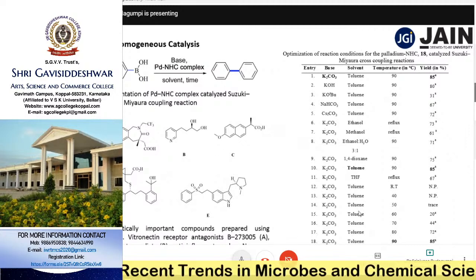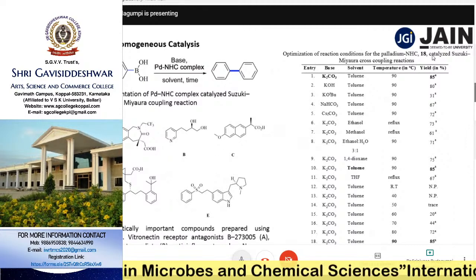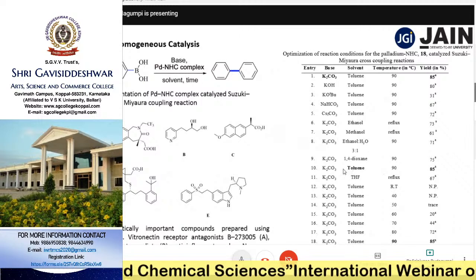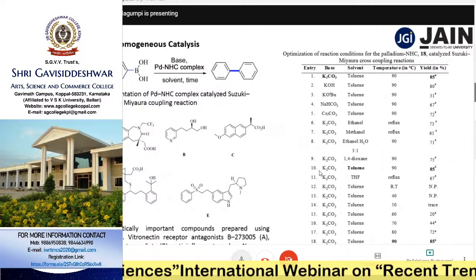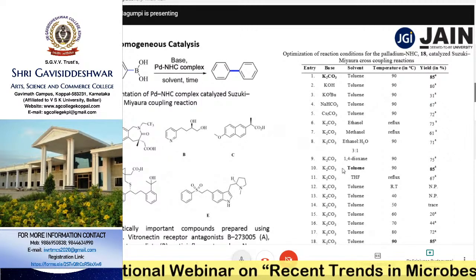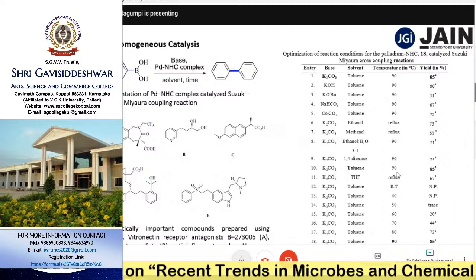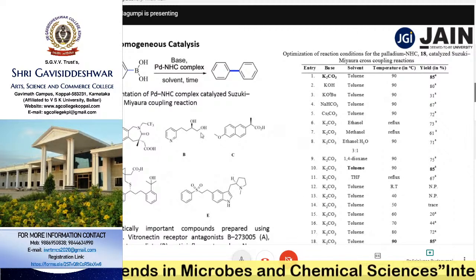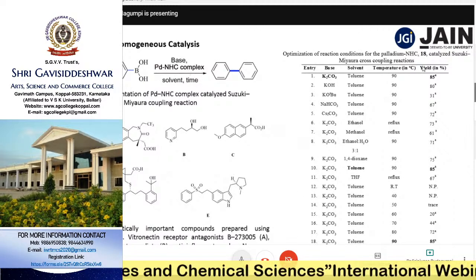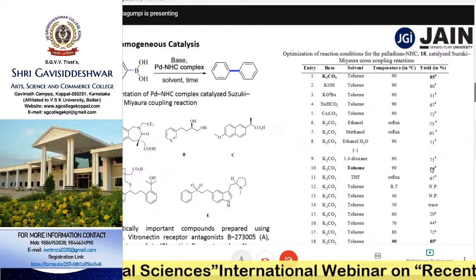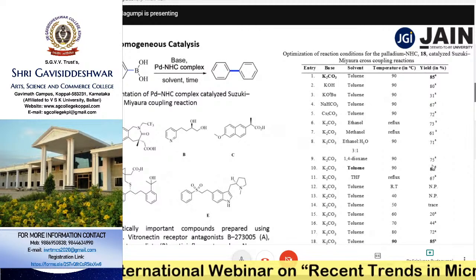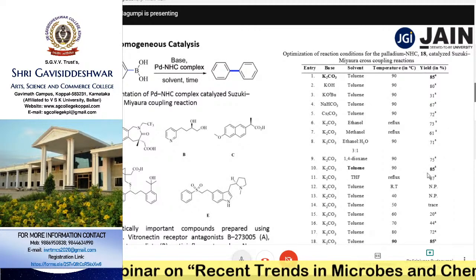So this is our catalyst optimization using complex number 18, which showed that potassium carbonate is an appropriate base and toluene is an appropriate solvent. The reaction was run for 4 hours in the presence of this particular catalyst. That has given us 85% conversion, that has given us 85% yield.